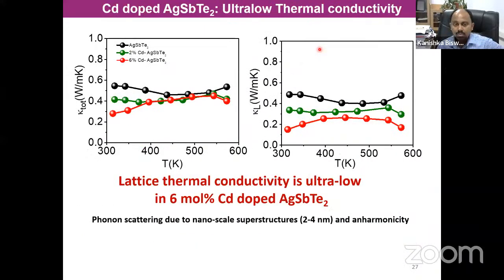So then we have measured the high temperature thermal conductivity, because that is the important thing to estimate the ZT at high temperature, which can actually go to the application. So you can see the lattice thermal conductivity data. This is the pristine sample, which is flat at high temperature, because the phonon mean free path is very low in this material.